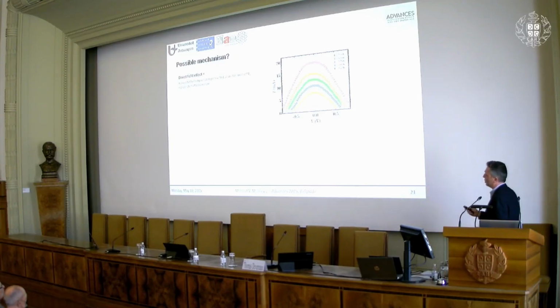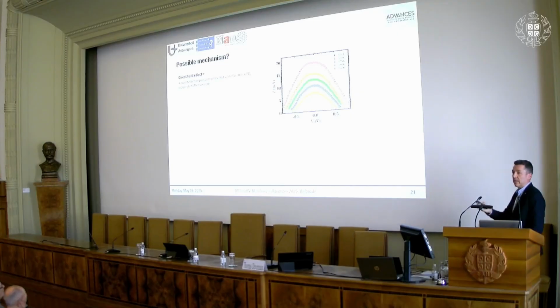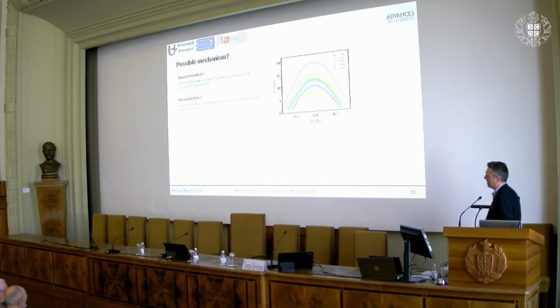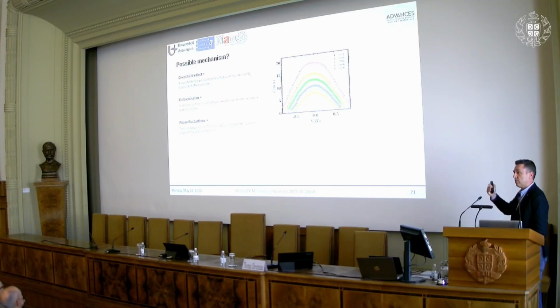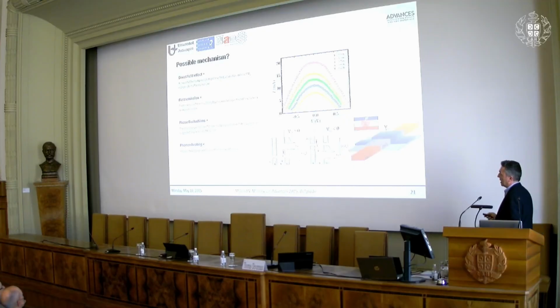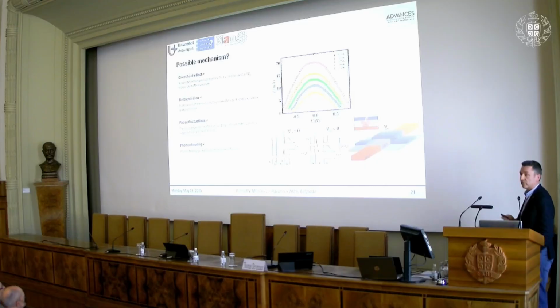We don't have a direct field effect, because otherwise we would have a symmetry between different polarities of the field. So we eliminated that. The direct emission of high density carriers from the gate directly to the superconductor is not possible because our oxide thickness is still sufficiently thick. Phase fluctuations probably play a role, but not at all temperatures that we considered. So finally, we realized that it's only the phonon heating in the oxide that is important for this effect.